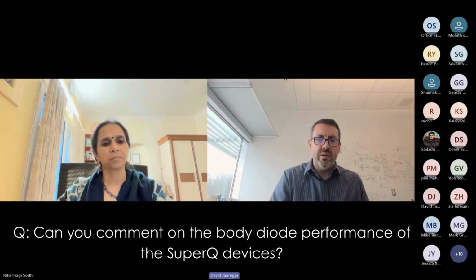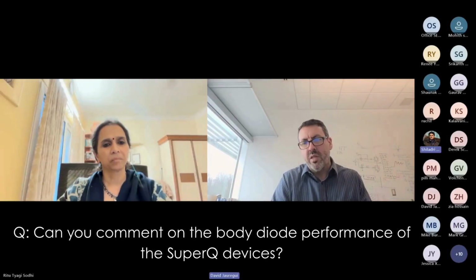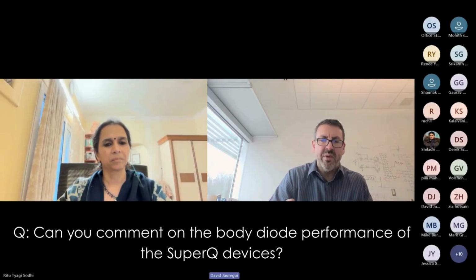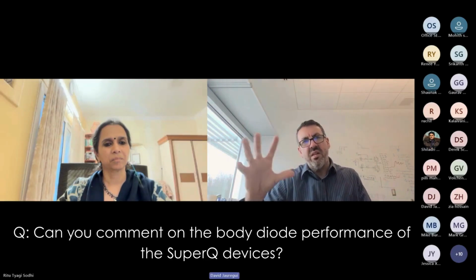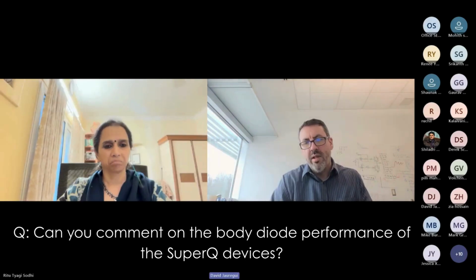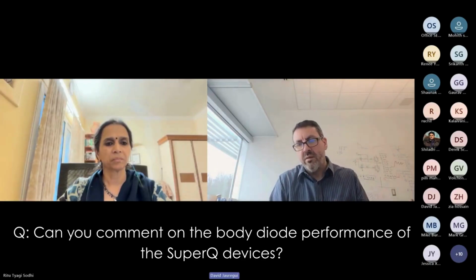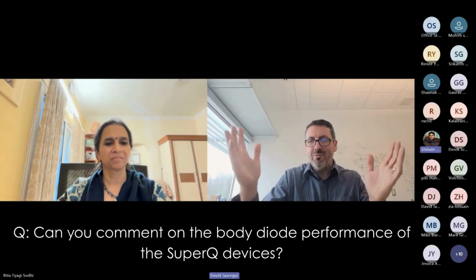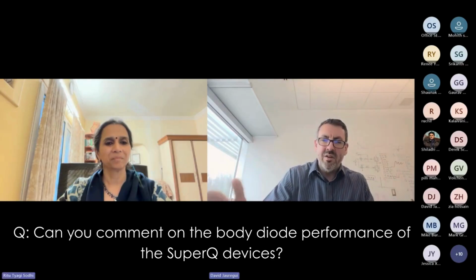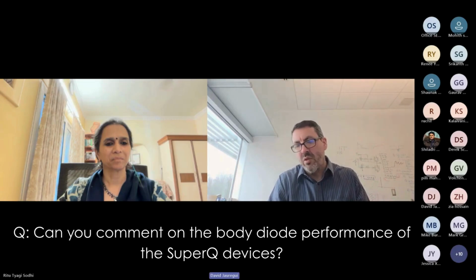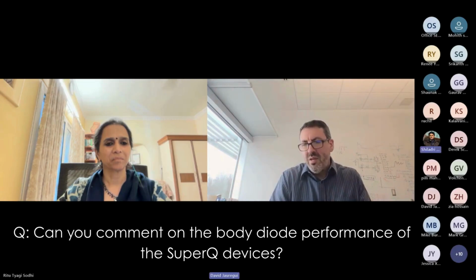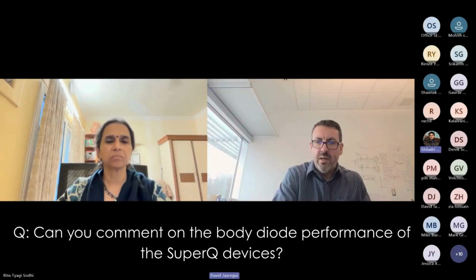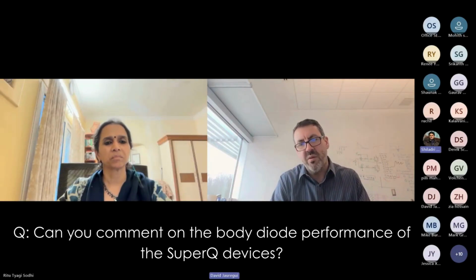Then it comes into the question of the ringing or the EMI. But when you get to those low levels of currents, then it's no longer a problem, because you have to realize that back when dead times were 500 nanoseconds to a microsecond, we went from MOSFETs having microcoulombs of QRR to, when GaN and silicon carbide came out, having no QRR. It's like, wow, great. Now we're down to the hundreds of nanocoulombs, probably even tens of nanocoulombs, especially if you start to adjust the dead time. You get to nanocoulombs that are still there, but it's no longer a first order impact. Switching loss, conduction loss, robustness, all these other things become a first order impact.